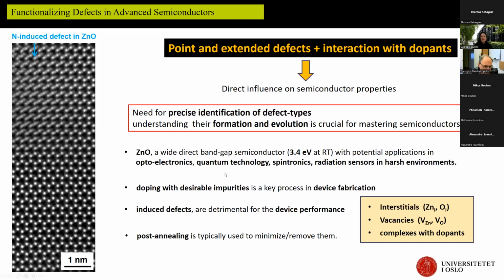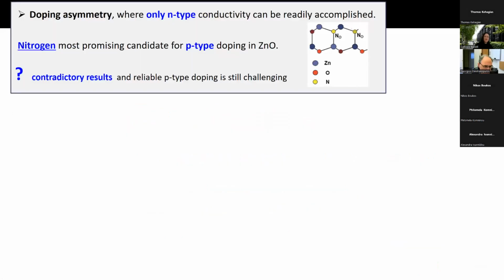Here, we will focus on an example of zinc oxide, which is a wide and direct bandgap semiconductor with potential applications in optoelectronics, quantum technology, spintronics, and radiation sensors. The motivation that triggered our study is the doping asymmetry that zinc oxide exhibits, where only N-type conductivity can be readily accomplished. Nitrogen, which is the most promising candidate for P-type doping in zinc oxide, exhibits very contradictory results so far, hence reliable P-type doping is still a challenge.